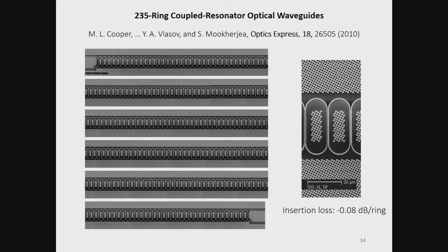It's certainly possible to lithographically make very long coupled resonator waveguides. And so we have made, this was the work with IBM, 235 coupled ring resonators. And as our paper will show, light propagates through this. You can see stop bands and pass bands. This is not just some amplified spontaneous emission going through it. It's coherent light. Light preserves coherence going through the sequence.